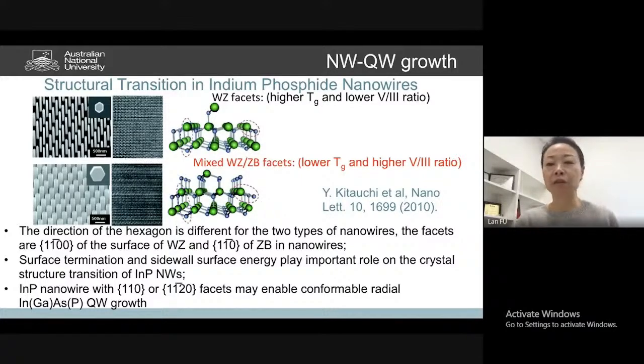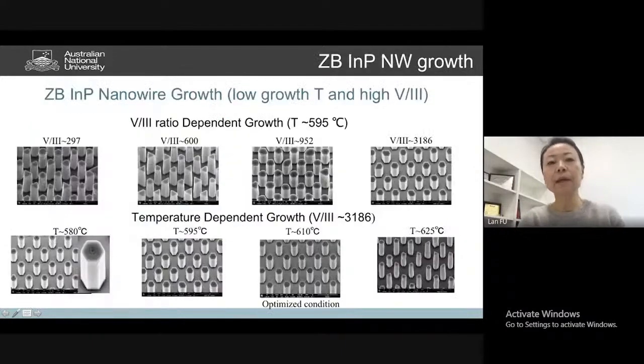And indeed, the literature supports that, saying that if you change your growth window by growing the nanowire at lower temperature and higher V/III ratio, you can rotate this hexagonal shape by 30 degrees. So you can pay some attention to that. You can see that with the same alignment, you can rotate a nanowire facet by 30 degrees, just by changing the growth temperature. So my student started really looking at the mixed phase, zinc blende dominant, nanowire growth by changing growth temperature and also the V/III ratio.